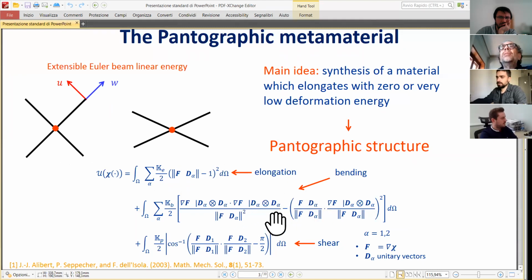And this is the bending term, which involves the gradient of capital F, therefore the second gradient of placement. So even if the technical details are not very important in this context, giving this energy, I have found a microstructure which, once homogenized, gives you this deformation energy.